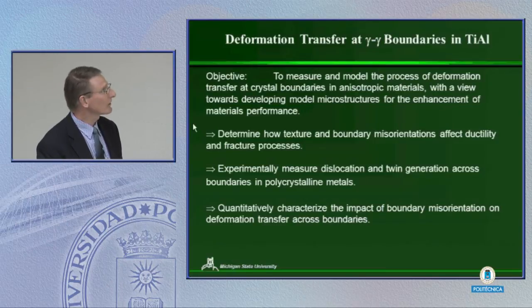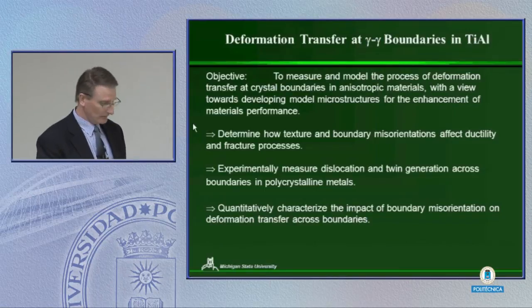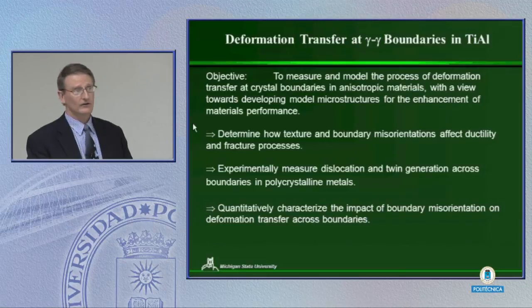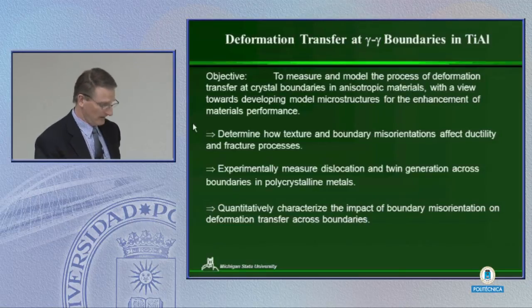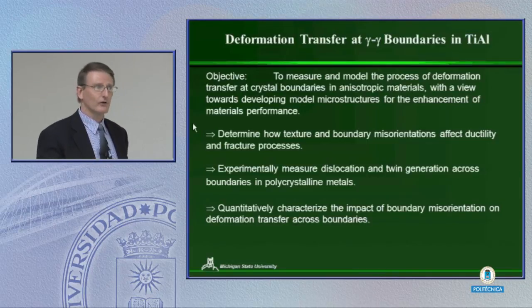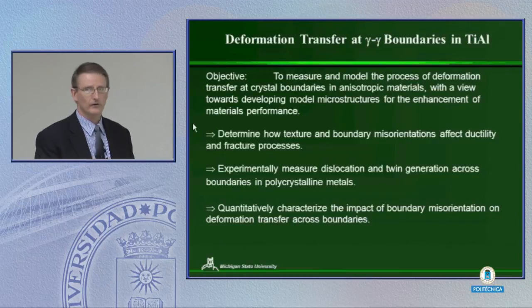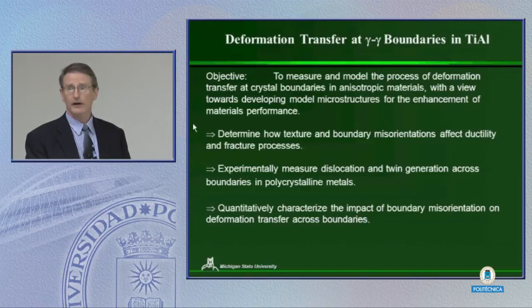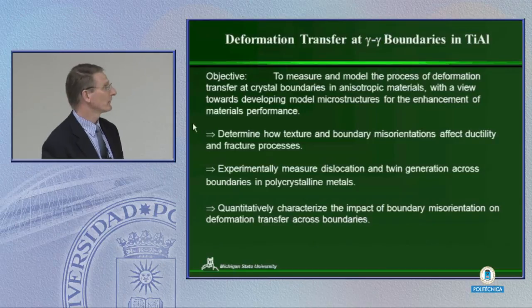Okay, and then I can talk a little bit more detail about TiAl. This is just a gamma alloy. And we've spent quite a bit of time talking about deformation transfer in this alloy. What we're trying to do is really understand the processes of what happens at a grain boundary in terms of if we have a dislocation pile up or a twin piling up at a grain boundary, how does that transfer deformation into the next grain? And are there some grain boundaries where that happens easily? Are there other grain boundaries where that is more difficult? And particularly, are there some grain boundaries that are susceptible to damaging through this process?